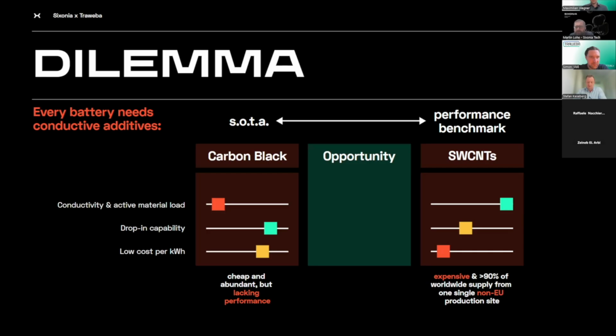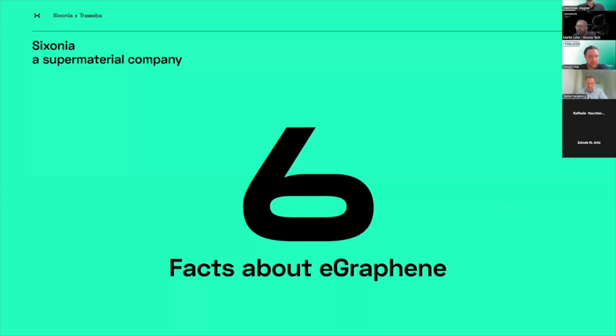And on the other hand, you have the single-walled carbon nanotubes, which really excel in terms of electrical conductivity and making your electrode conductive. So you need only very little. But on the other hand, they are super expensive, and basically 90% of the worldwide supply of this material is located in a single production site, and this is not inside the EU. So in between there, we have an opportunity. And I think that our e-graphene perfectly fits in this space. And I will tell you 6 facts about it and hope to spark your interest and see if we can work together in the future.